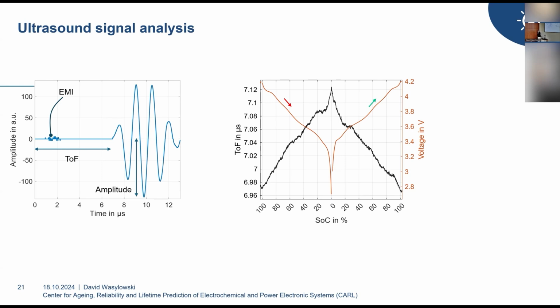And we know from physical fundamentals that the time of flight is closely linked to the Young's modulus and density of the cell over the speed of sound. So we can just look up this equation which connects these two parameters. And if we insert our time of flight values into this equation, we can calculate the Young's modulus. So when we have a high time of flight, typically occurring at low states of charge, we have a low Young's modulus, which is this rubber ball behavior. And when we have low time of flight values at high states of charge, we have this high Young's modulus, which is this rock behavior.